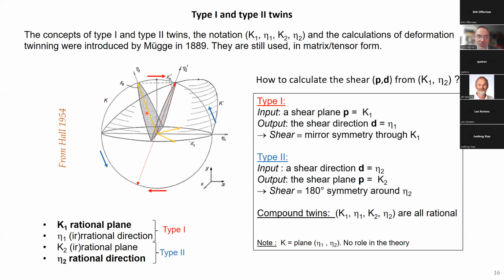around this direction. Okay. In the first case, type 1 twins are mirror symmetry through a K1 plane, and this is the type 2 twin. The relationship between the parent and the twin phase is a rotation, it's a twofold rotation around this direction here.